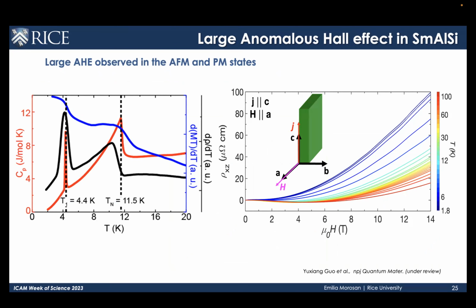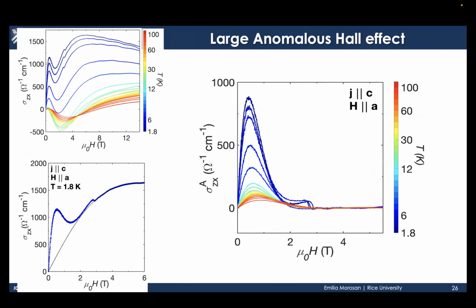But now when we look at all data up to 14 Tesla for different temperatures, starting from low temperature blue over here, increasing through the magnetic order, the anomalous Hall is still large, both in the antiferromagnetic state and the paramagnetic state. It's maybe easier to see if we convert to conductivity, and that's what I'm showing here, where I'm illustrating with the black line how we account for the normal conductivity in a two-band model for this particular compound as our best estimate of the anomalous Hall contribution.